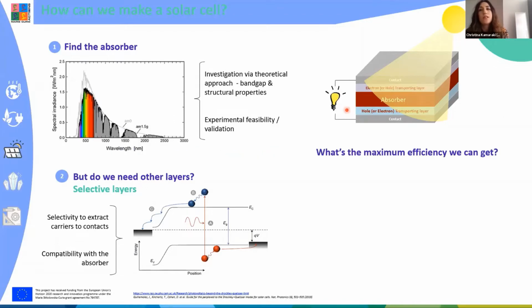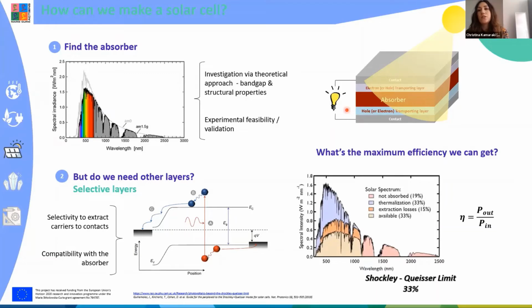So let's think how much energy actually we can absorb and what will be the efficiency of our solar cell. The efficiency is defined as the ratio of the power output, which is actually a product of voltage and current, over the power input. Unfortunately, we cannot have efficiencies 100% or 90% because there are some inevitable losses. First of all, the major loss is the so-called thermalization loss. So this loss stems from the high energy photons. As we mentioned before, when a photon of high energy is absorbed, then the electron has higher kinetic energy, which is excess and we cannot exploit it. So it's lost as heat.